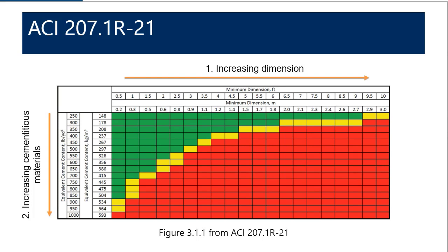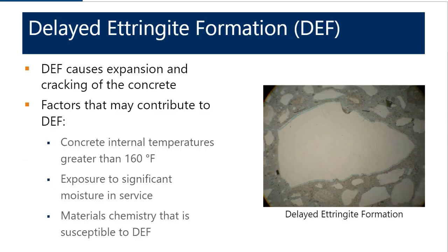So the risk of exceeding the maximum temperature is the risk of DEF happening. DEF requires a few different factors, which Jacob had talked about earlier. Let me pull up that slide really briefly. So it requires, first of all, temperatures exceeding 160 or whatever the maximum is for the project. But it also requires exposure to significant moisture in service and a materials chemistry that's susceptible to DEF.